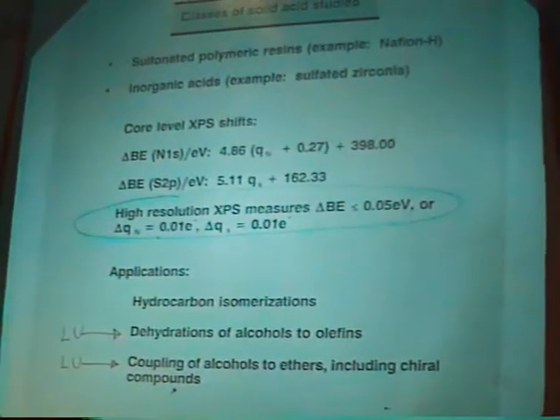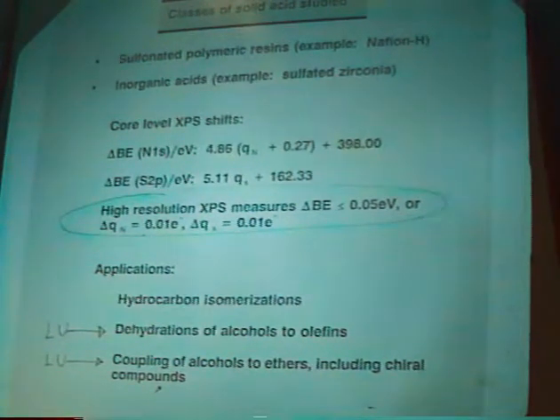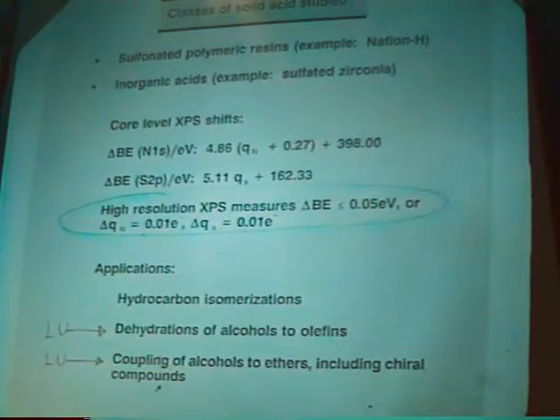A similar correlation exists for sulfur, which is the source of sulfonated polymeric resins and sulfated zirconia of both Lewis and Bronsted acidity. These are the two systems we're concentrating on. We can express the core level XPS shift from previous graphs in limited region, so that if we can measure the binding energies to within 0.05 electron volts with high resolution, it's claimed by Al Miller in our lab that you can do it to within 0.02 eV, then charge changes of the order of 10 to minus 2 electron charge are detectable. Therefore, you can not only clearly distinguish between Bronsted and Lewis acidity, but you can also tune in on whether the Lewis acidity is stronger or weaker.